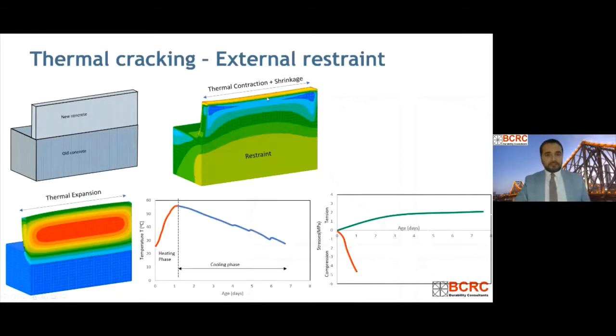Now all these thermal contractions and shrinkage are restrained by this old concrete, right? And the degree of restraint will depend on the size of both elements, and the type of concrete that we're using, the elastic moduli. So it develops tensile stresses in the new concrete, right? Our compressive stresses gradually change to tensile stresses, right? And as soon as they exceed the limited tensile strength capacity at early age, cracking occurs. So this is the whole mechanism behind the external restraint cracking.